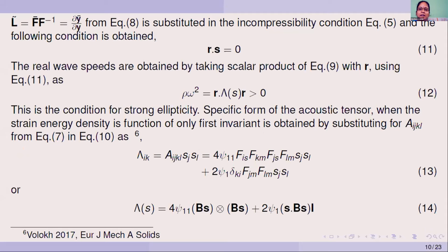So this condition of strong ellipticity is violated for the vanishing wave speed, that is when this rho omega square becomes 0. This physically means the inability of the material to propagate a superimposed wave, as a crack tends to localize in a direction perpendicular to a possible wave direction.